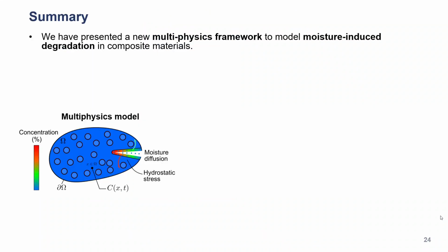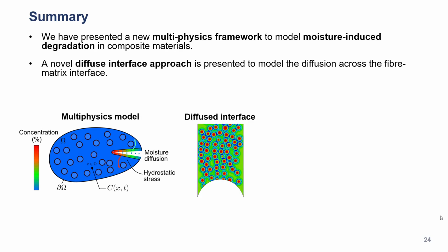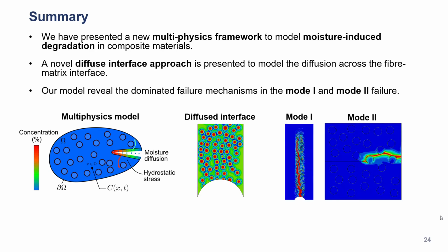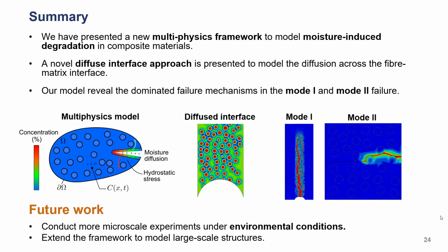In summary, we have presented a new multiphysics framework to model the moisture-induced degradation in composite materials. A novel diffuse interface approach is presented to model the diffusion across the fiber matrix interface. Our model revealed the dominant failure mechanisms in the mode 1 and mode 2 failure. Our future work will focus on conducting more microscale experiments under environmental conditions and also extending the framework to model large-scale structures.